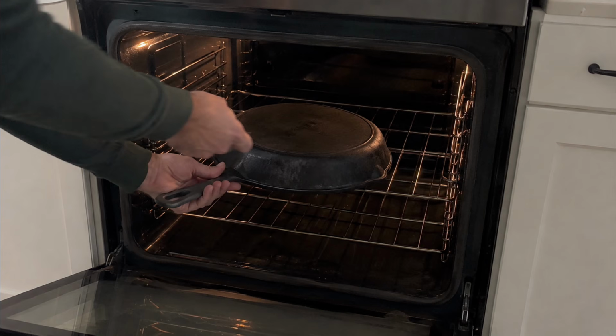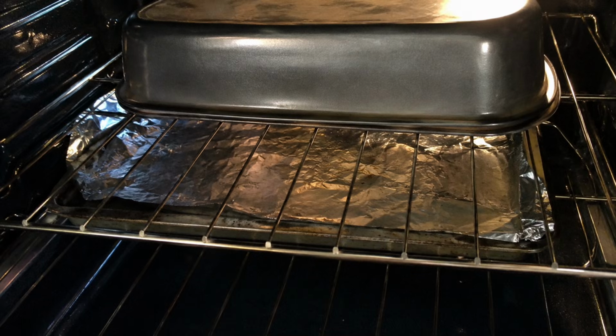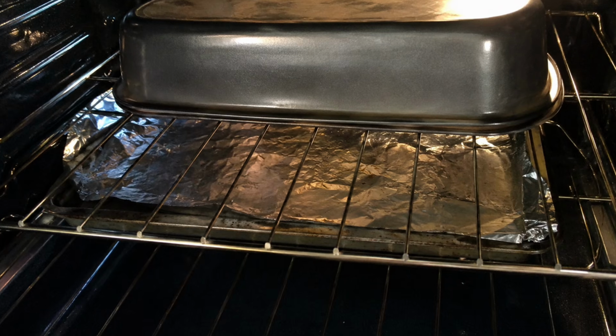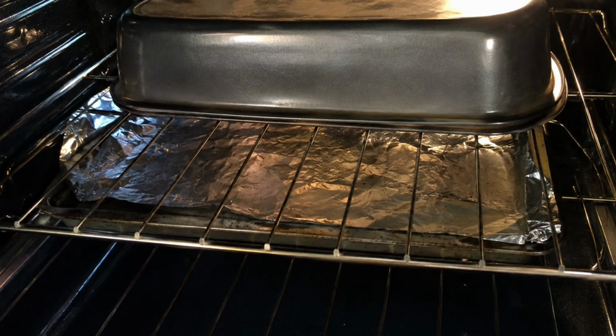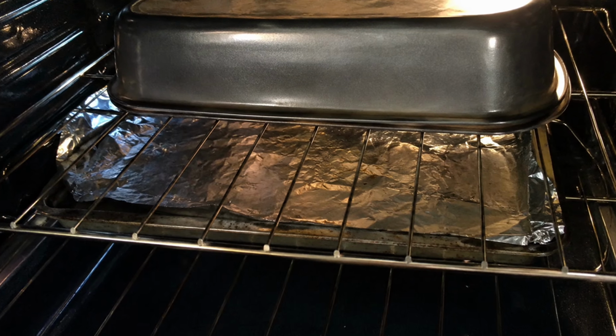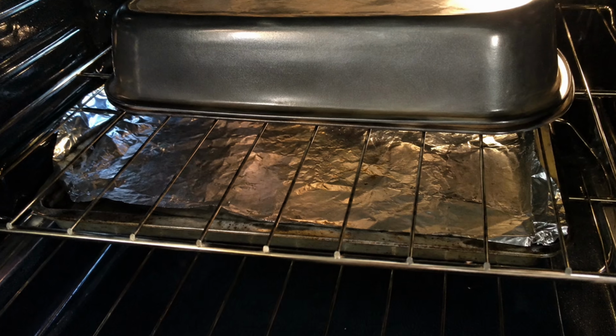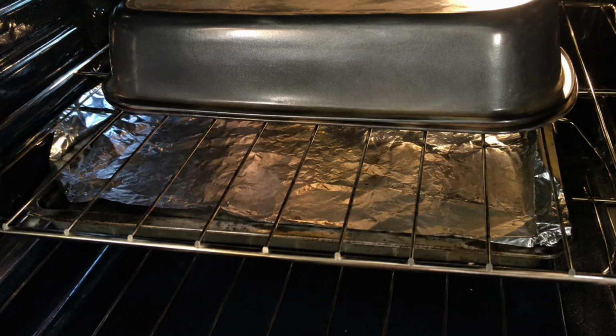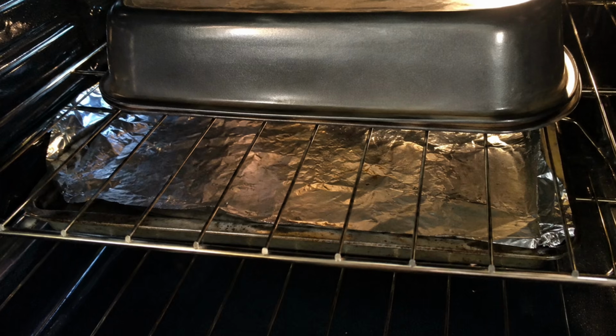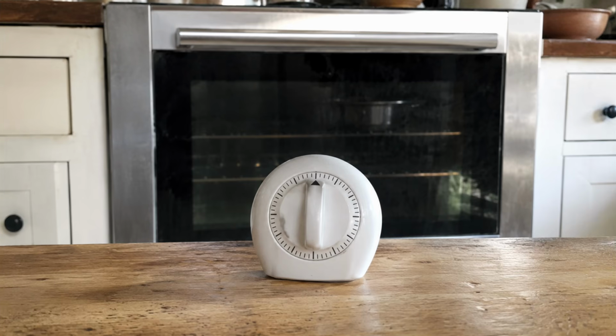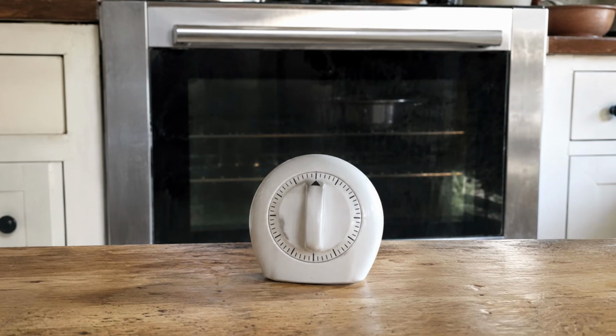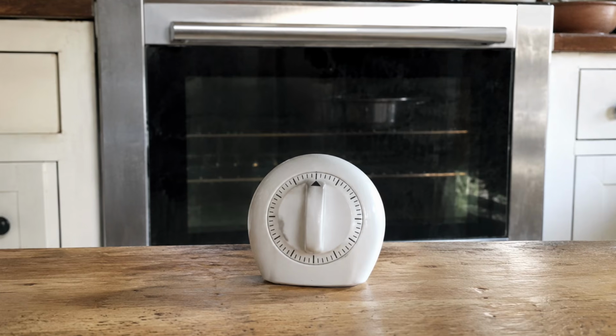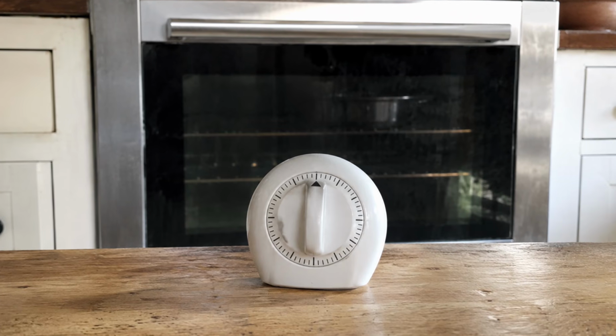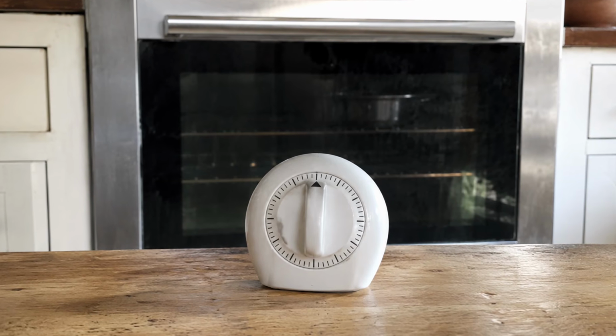Then the cure. Set the pan upside down in the oven, a sheet of foil or a tray on the rack below to catch any stray drip, and bake it hot, up around 450 to 475 degrees for a full hour. Upside down, so nothing pools. A full hour so the layer hardens all the way through, for a half-cured layer is a sticky layer. Time matters as much as the wiping. Then shut the oven off and let the pan cool down inside it, slow, on its own.